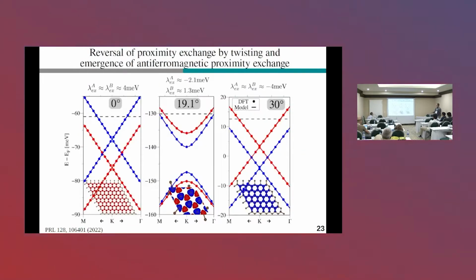And now this is a summary of our most important findings. So for 30 degrees, we have already seen what's going on. We have this negative spin polarization. Spin-down Dirac states are pushed to lower energies, and these are the corresponding exchange parameters for our model. Now, if we go to the 0 degree case, we find exactly the opposite. This is really remarkable. Spin-up Dirac states are pushed to lower energies. And if you calculate the spin polarization, it's again uniform but positive on the graphene. So you can essentially reverse the proximity exchange by twisting.